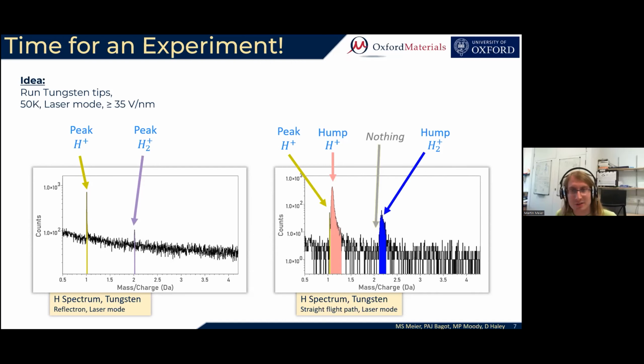And then let's check the mass charge 2 peak. And what we find is there is no peak at all. There is only a hump. So all of the H2+ that we see in these experiments is evaporating with an energy deficit.